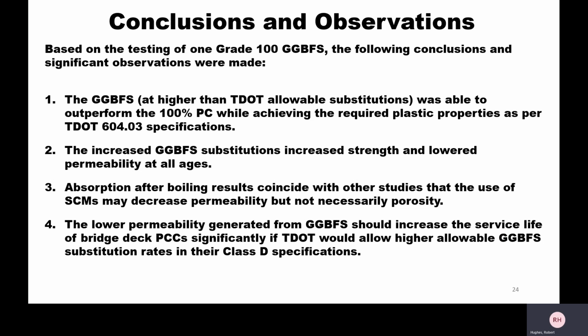So let's get into some conclusions here. Based on our testing of one sample of grade 100 GGBFS, we can say that the slag we used, although it was higher than the TDOT allowable substitution, was able to outperform the 100% PC while achieving the required plastic properties set forth by TDOT 604.03. The increased substitution levels increased the strength and lowered permeability at all ages, even though strength was a byproduct of what we were trying to achieve in lower permeability. The absorption after boiling results coincide with other studies that SCMs may decrease permeability, but not necessarily porosity, and the lower permeability generated from GGBFS should increase the service life of bridge deck PCCs significantly if TDOT would allow higher allowable GGBFS substitution rates in their Class D specs.